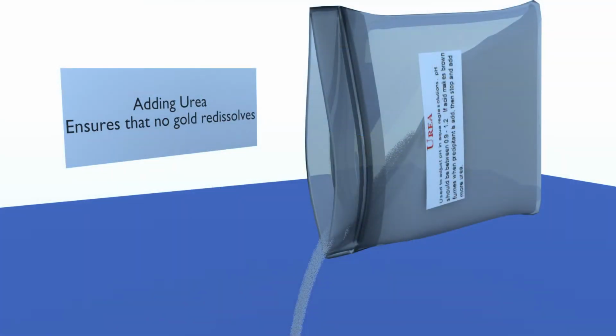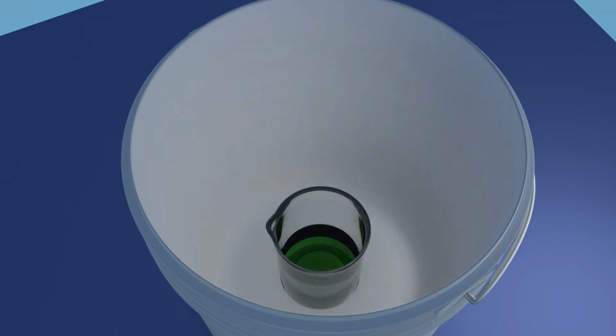Adding urea. Free nitrogen ions can cause some gold to redissolve after it is precipitated out of solution, resulting in gold losses. No worries, adding urea neutralizes all these ions, ensuring that the gold does not redissolve. Place your beaker in a clean white plastic bucket. Though overflows are not common, the bucket will contain the solution if an overflow occurs. Add urea to your solution.